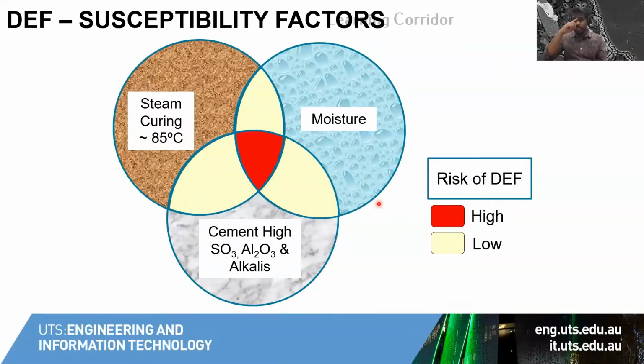But the good news is we need all the vital factors together to cause DEF-related durability issues. Say concrete made with high sulfate, aluminate, alkali cement that needs to be steam cured at very high temperature for a longer time. And then the concrete will have to serve in an environment where direct contact of water is there or high humid condition is there.